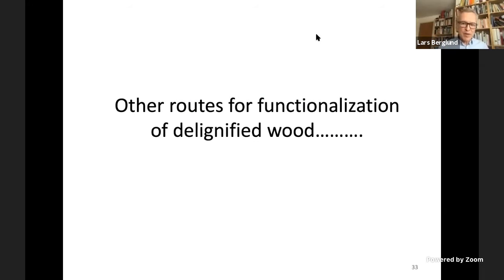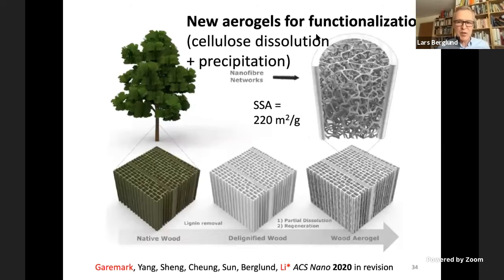I wanted to finish off with some examples of other routes to functionalization of wood. This is work by Jonas Garemark and Junjun Li primarily. So what they do is take the delignified wood scaffold, and then they partially dissolve the cellulose and precipitate it. So they manage to create an aerogel structure inside the lumen, and they measure a specific surface area of 220 square meters per gram. And that, of course, is very interesting for functionalization purposes.